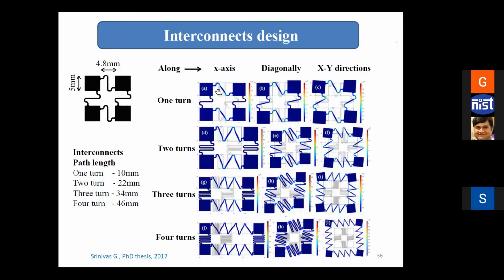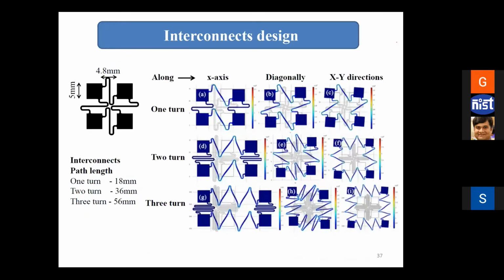Suppose this is just a straight line which is not stretchable, and if you start stretching it to 300%, this interconnect would break, right? So don't keep it like a straight line, but convert it into a spring-like format, so that when you stretch it till 300%, it opens up and it allows these rigid islands, these blue blocks over here, to be stretched up to 300%, right? Because if interconnects are not stretchable, the system as a whole would not stretch. And these are all COMSOL simulations, where we tried to show what kind of design we can take for interconnects.